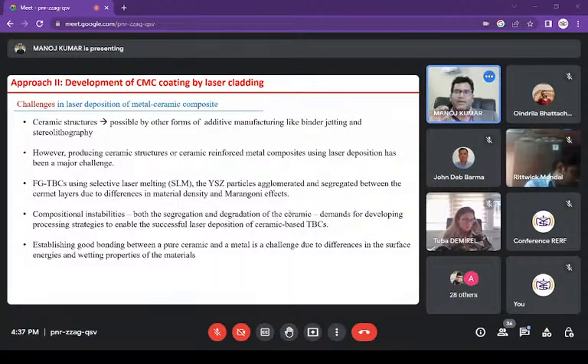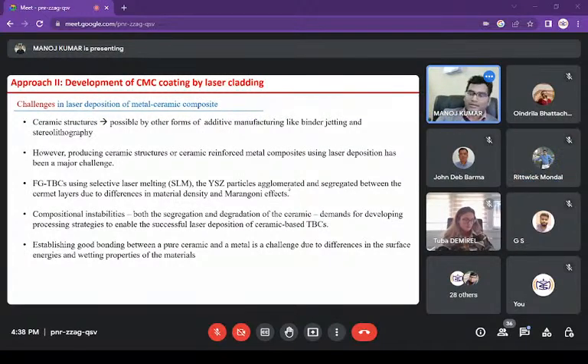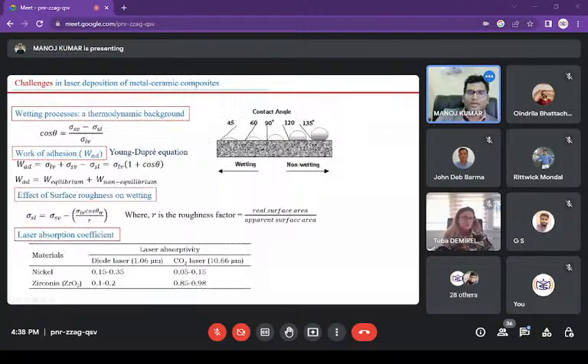So we can have more metal on the first layer of the metallic substrate and slowly increase the composition of oxides, and on the top we can have 100% oxide. So that was the hypothesis, the idea we wanted to work upon. Unfortunately, that did not work, for the same reason that I'll cover. So let me first tell you the problems.